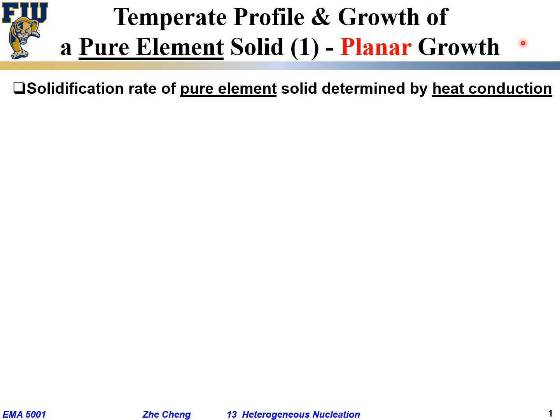Another topic that we want to talk about is related to the global or microscopic features, which is related to the temperature profile and growth for pure element solid. Okay, and we said for pure element, the solidification, or specifically the growth of existing solid into the liquid, quite often would be determined by heat conduction. How much of the heat can be extracted away from the system determines how fast the solidification happens, or how fast existing crystal would grow into the liquid.